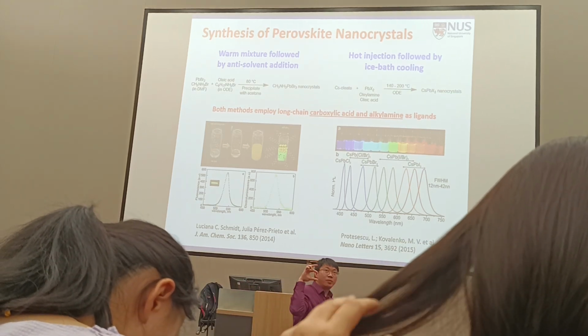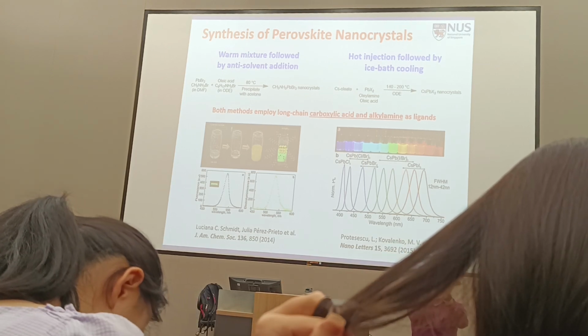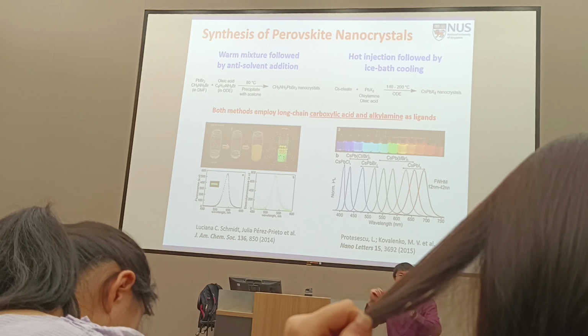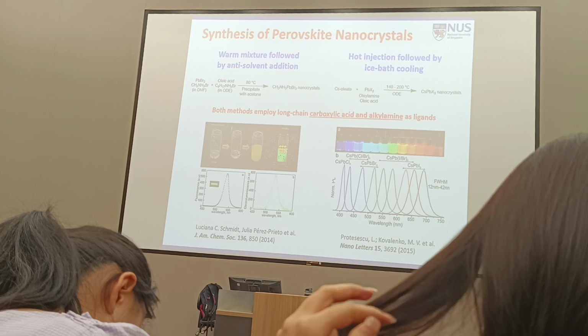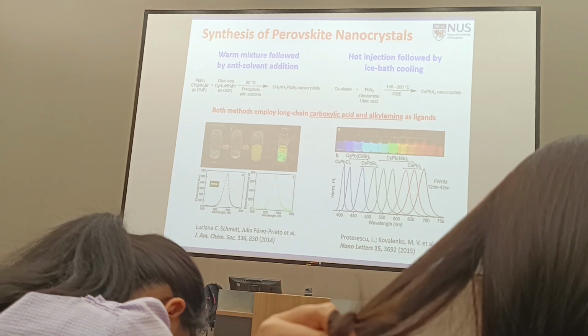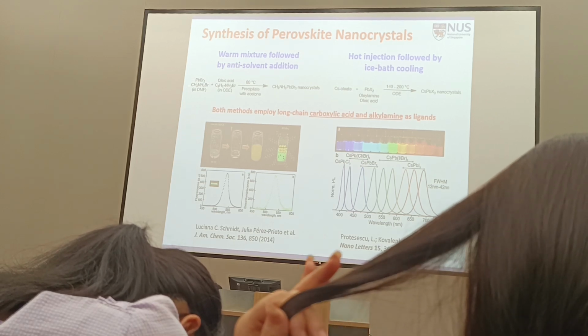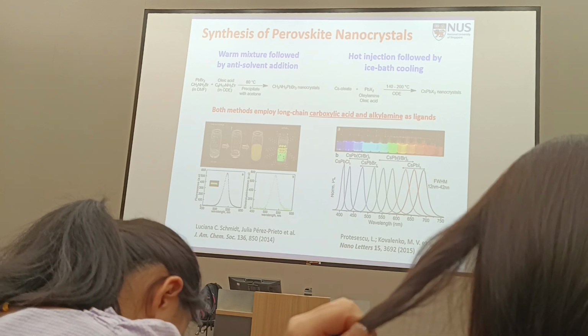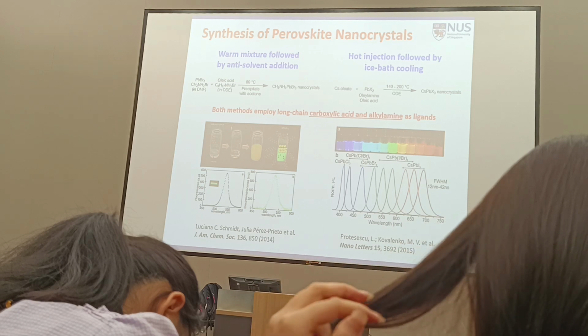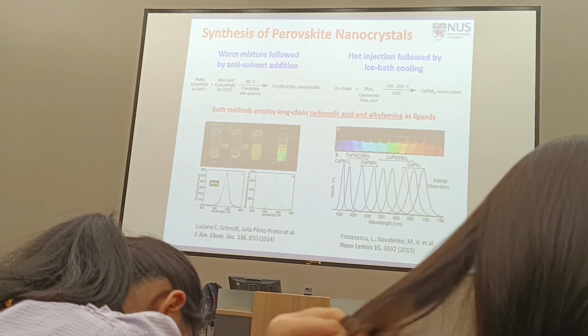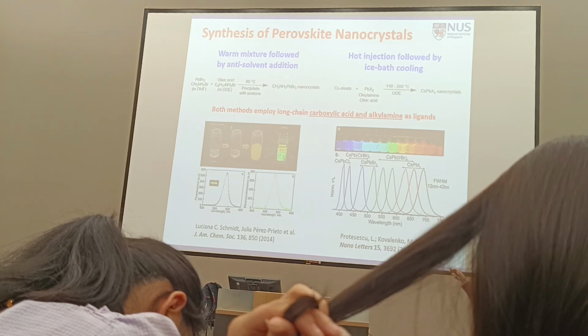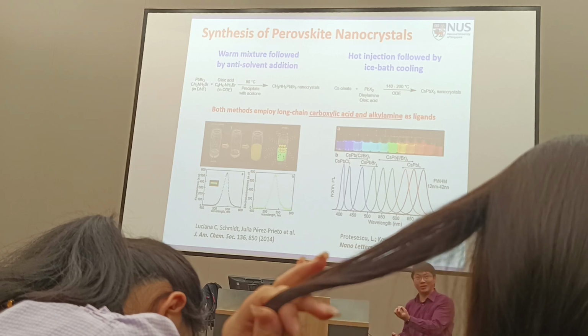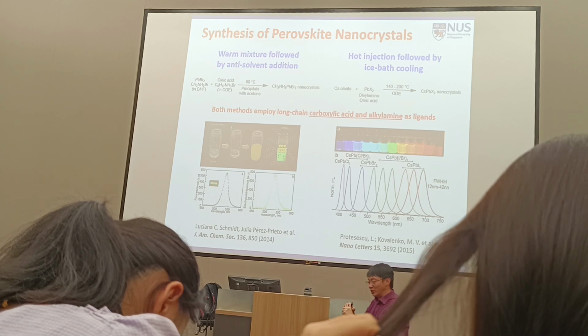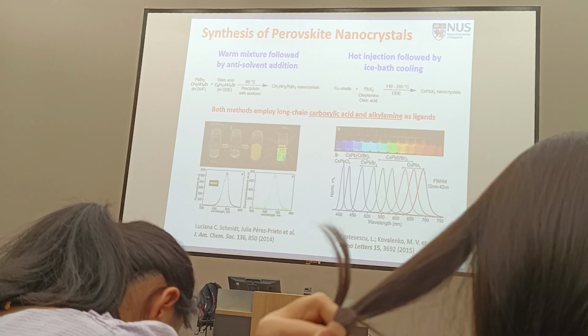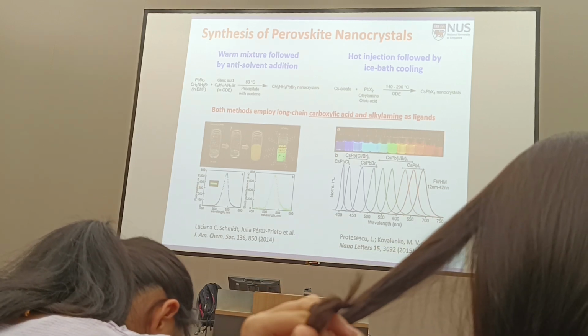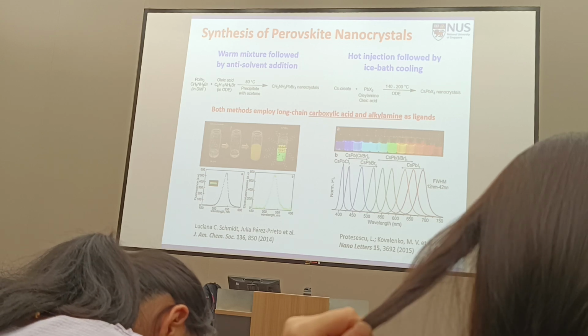Now this carboxylic acid group and the amine group will coordinate to the surface of this crystal and allow the entire crystal to be soluble in an organic solvent. Basically, the first people who synthesized this mixed all these ingredients together: lead halide, methyl ammonium halide, the ligand oleic acid, the ligand oleylamine, and they have a warm solution. They put it into an anti-solvent to precipitate out tiny little crystals. Once these precipitate out, they can collect them and disperse them in an organic solvent. The anti-solvent is acetone.